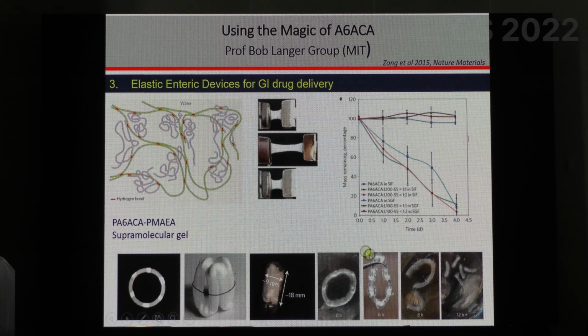And this polymer, which is our polymer, actually stays. It doesn't degrade in the stomach low pH condition, but starts degrading in the intestinal high pH conditions, and as it degrades, it releases the drug. So if you have a drug that you want to release only in the intestine, not in the stomach, these are the kind of devices called the enteric devices, which Bob Langer developed, and he also showed that you have to have that beautiful hydrophobic balance with the hydrophilicity in order to make a device like this.